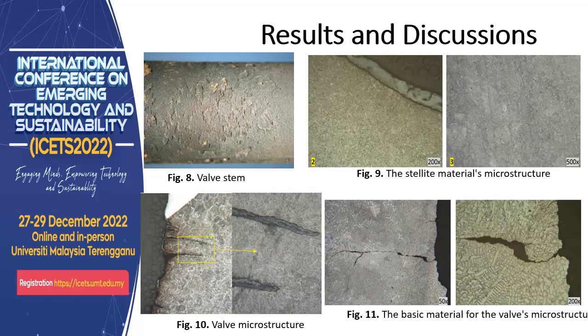In the stellite material microstructure, thermal fatigue corrosion occurs where the valve material area and stellite material meet. It is evident that a deposit product bearing signs of high temperature corrosion attack has formed at the end of the fracture. There is some high temperature corrosion of the valve base material, while valve material and gas on the stellite layer also affect it.